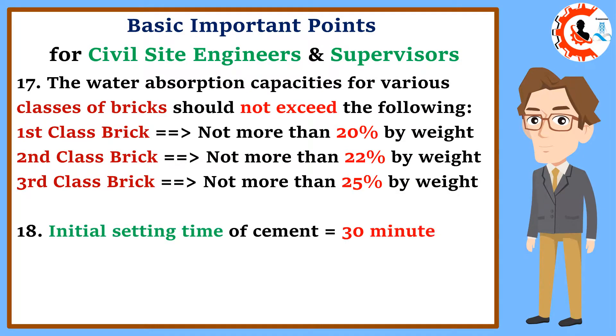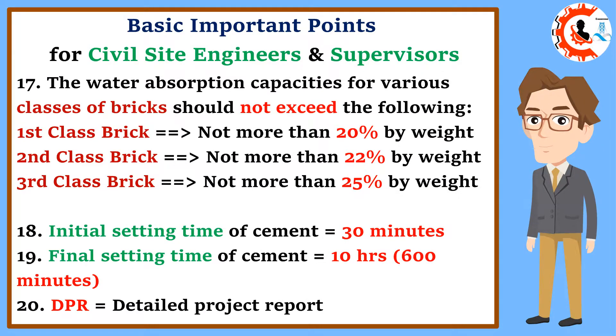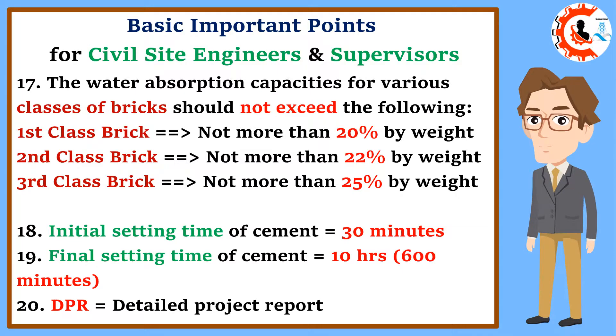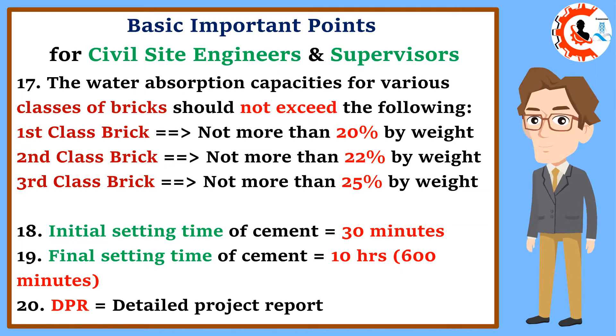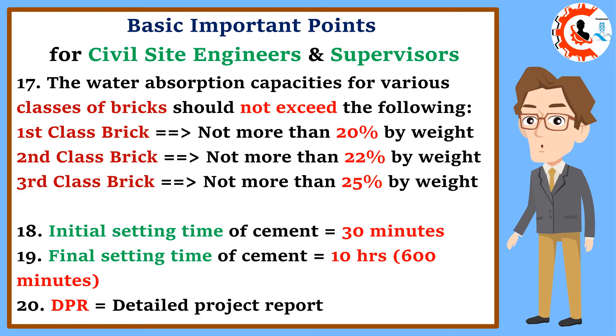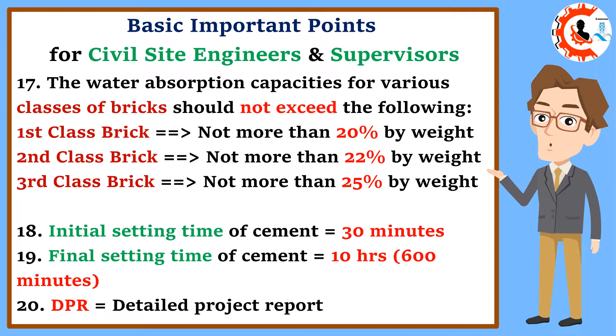17. The water absorption capacities for various classes of bricks should not exceed the following: 1. First class brick — not more than 20 percent by weight. 2. Second class brick — not more than 22 percent by weight. 3. Third class brick — not more than 25 percent by weight.